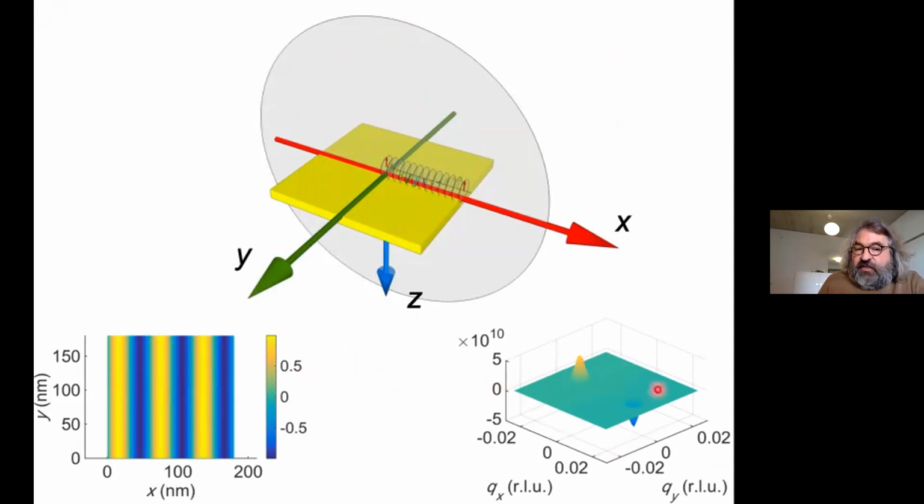And on the bottom right-hand side, you see the two diffraction peaks with a small twist. And the small twist is that this is a dichroic diffraction peak plot. So what we do is we subtract the intensities obtained for the two opposite polarizations. And so we have here, in this case, a positive diffraction peak and then a negative diffraction peak.